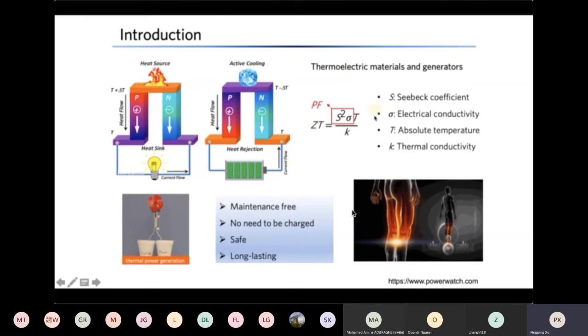And the ZT, if you have high ZT, you can have high performance with the cooling effect or the power generation. And the ZT is dominated by three other key parameters: the Seebeck coefficient, sigma, the electric conductivity, and the thermal conductivity. So typically, people want a high power factor, meaning the Seebeck coefficient squared times electric conductivity. And we also want the thermal conductivity lower. But there are two conflicts. If you have a high Seebeck, you have to have a lower conductivity. If you have high conductivity, you have to have a high thermal conductivity.